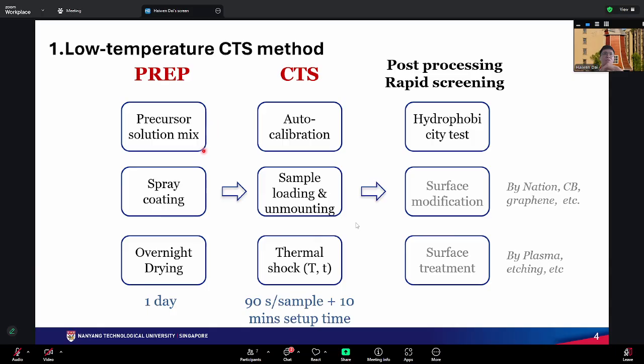The preparation is very simple. Actually, a lot of people in the group can do this much faster than I do. First we prepare the precursor solution mixture. We spray coat the solution mixture over the substrate, and then we need to dry it overnight on a heating plate at about 80 degrees Celsius to ensure it is 100% dry. After that, a lot of people have used the script I have been writing. It has automated calibration and sample loading and mounting. It is basically pushed by a time bar, so each sample needs to be finished in 90 seconds. The thermal shock is also arranged by the program I have written.